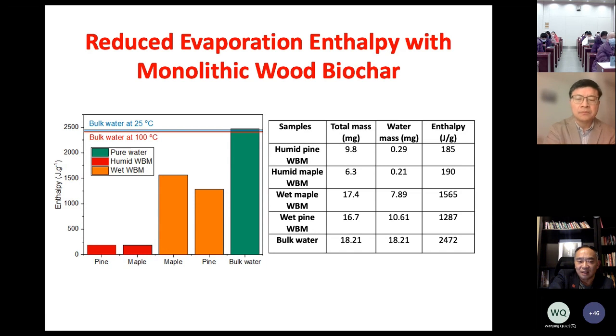Okay, you can see that the difference is huge. If you look here, the bulk water is about 2,500 joules per gram of water evaporated at 25 degrees C. But if it's wet biochar, it can be reduced to, let's say, about 1,000. If it's just humid biochar, even lower. Okay, this is the fundamental reason that we can have a case with an efficiency over 100%: it basically lowers the energy barrier for evaporation.